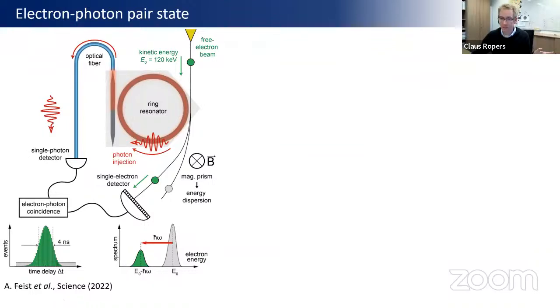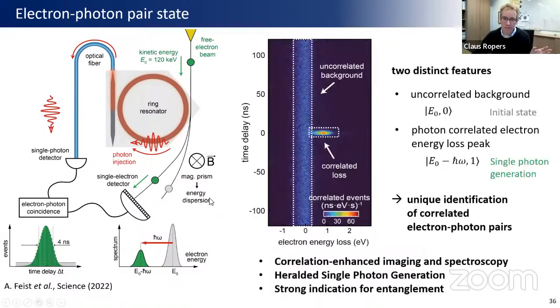We can now do coincidence measurements, basically, between the electrons impinging on the detector after the electron spectrometer, so resolved in terms of energy, coincident with photons produced and recorded coupling out of this resonator. Yeah. So what this now allows us to do is basically to do these coincidence measurements and measure the distribution of events, of electron events, the energy of each electron event, and the time difference between an electron event and the next photon that this photon detector has measured.